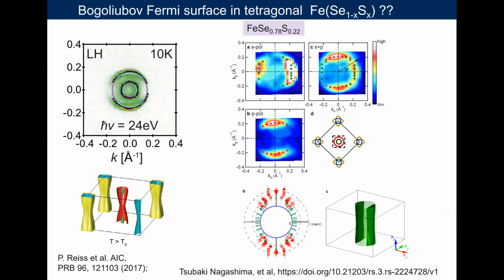Sorry, just to check that I'm understanding the picture: is the idea then that there are whole regions of the Fermi surface on which the superconducting gap is zero, but they're not Fermi arcs, they're actually reconstructed into pockets? Yeah, I think this will be a Fermi surface in the superconducting phase, is what they are claiming. So there is a finite density of states originating from this type of entities which form there.